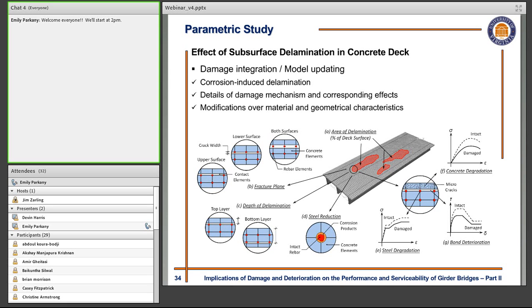Within the corrosion, reinforcement can experience corrosion from one side, and the corrosion can propagate all the way around to the other side of the reinforcement. So the fracture plane that can happen within the deck can occur at the upper surface, lower surface, or both surfaces of these corroded rebars. This is another detail that we need to include in our model. Delamination can occur as a result of corrosion in the upper layer of reinforcement or the lower layer of reinforcement. Other than that, another geometrical feature that we need to play around with is the reduction in the cross-sectional properties of the corroded rebars.